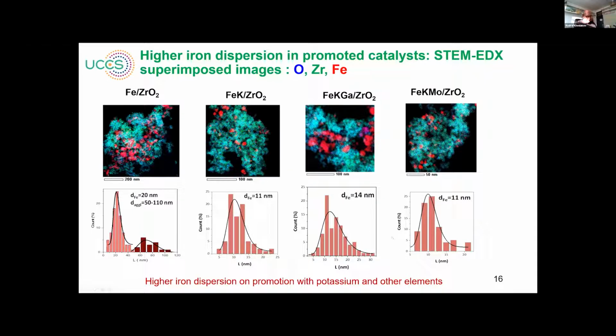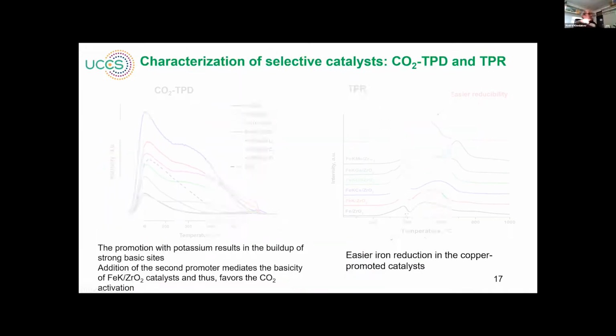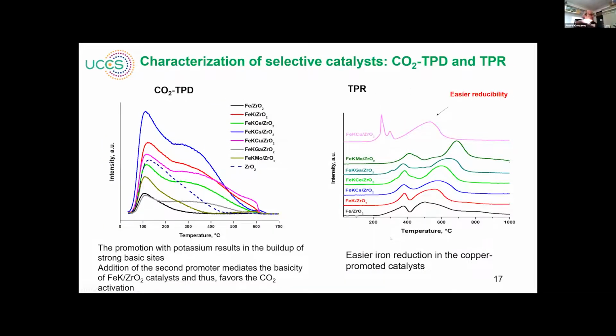So there is the effect of especially promotion of potassium: higher iron dispersion. The second characterization was absorption of CO2 to measure the basicity of the catalyst. And of course, we see that zirconia already has basicity. When we add potassium, for example here with cesium, we have a significant increase of basicity. However, when we add the second element, the second element mediates the basicity.